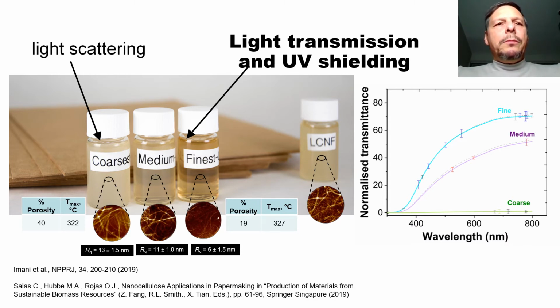You can see the values in the bottom of the atomic force microscope images that are here. So the coarser ones, of course, have higher roughness. The finer the fibers, the lower the roughness, but also the lower the porosity. And that means that we have here a way to leverage the property of the fibril fractionation by size to produce lightweight paper materials with different light scattering, different color, and of course different absorbency because the porosity is quite different. On the right, you can also see how the light transmittance can be quite different. In the case of the papers produced by the fine fibers, there is a more transparent structure. In the case of the coarser fibrils, then we have an opaque material.